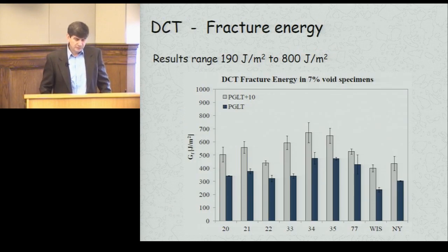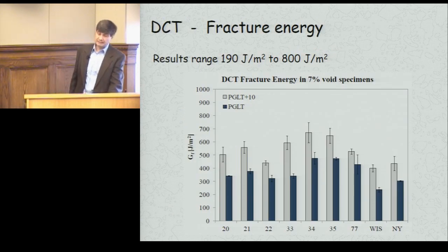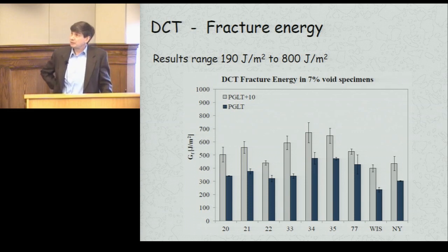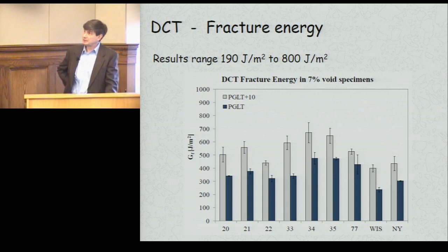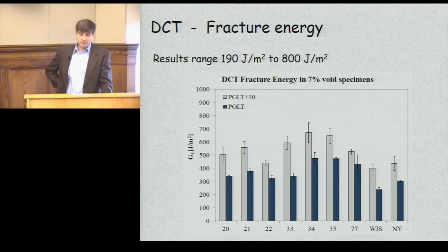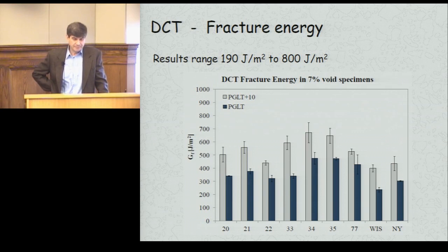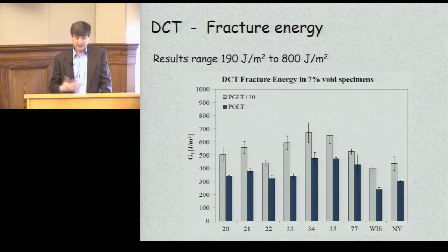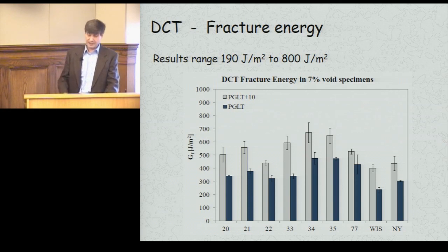Here I show some results of fracture energy obtained on different types of mixtures that we tested as part of the second phase of the pooled fund study. As you can see, we have values between 200 and 800. Of course, you will see immediately the huge temperature effect on properties of asphalt mixtures, including fracture.